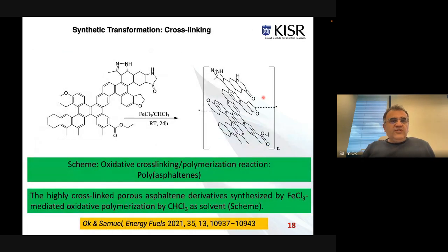So then we focused on modification of asphaltenes. What we did is work in chloroform, which is one of the solvents for asphaltenes, and we also worked with iron chloride, which is a catalyst material in this case.